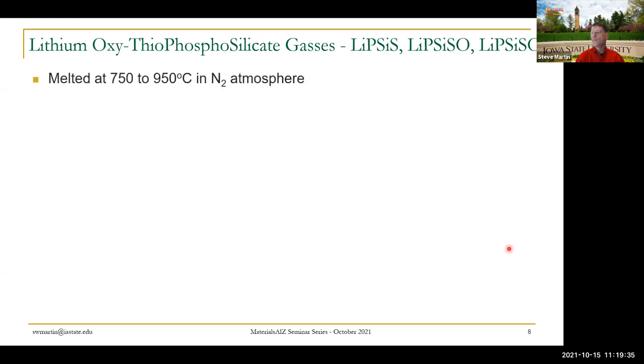We're in this family of lithium, silicon, phosphorus, sulfur. Beej and Pierre have listened to me talk about mixed glass former effects. So this is a mixed glass former. We use phosphorus because it's low cost. We use silicon because it's also low cost, but a great glass former. I've talked about oxysulfide compositions, and I'll show you one. More recently, we've actually begun working on mixed glass former, mixed oxysulfide nitride compositions. We started putting a little bit of nitrogen into our glasses, and I'll show you the beneficial aspects of doing this.